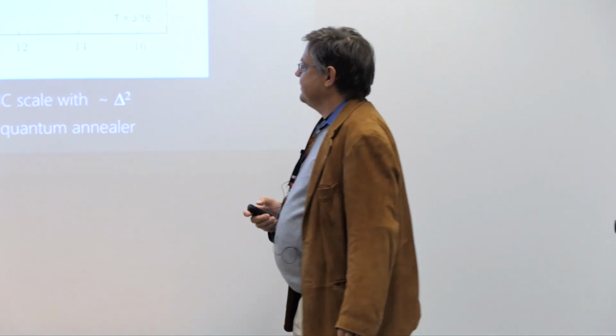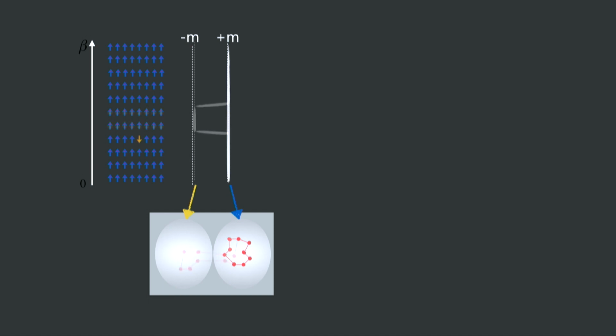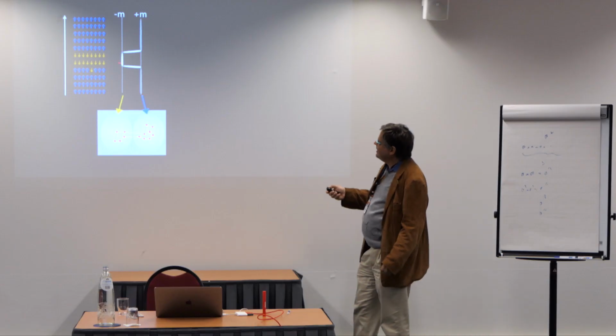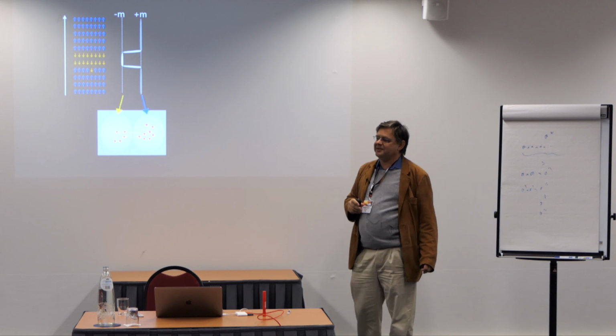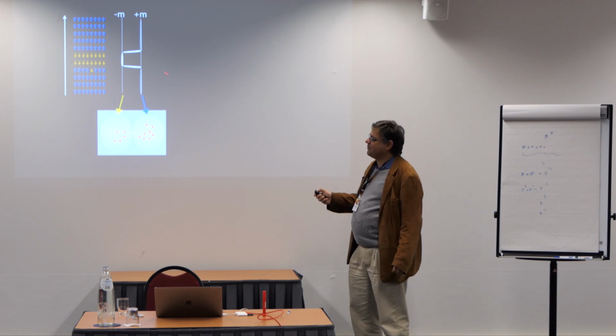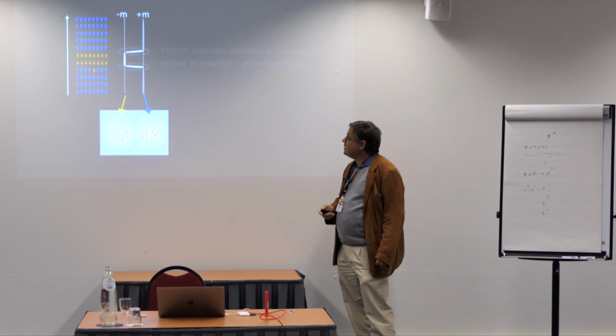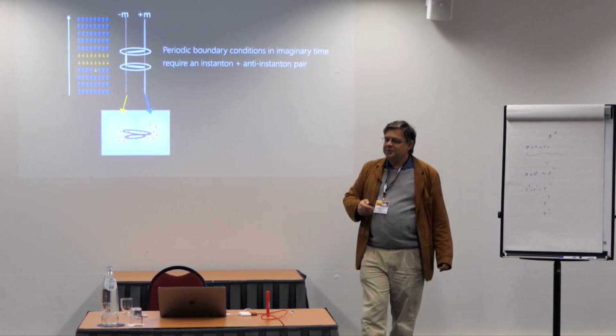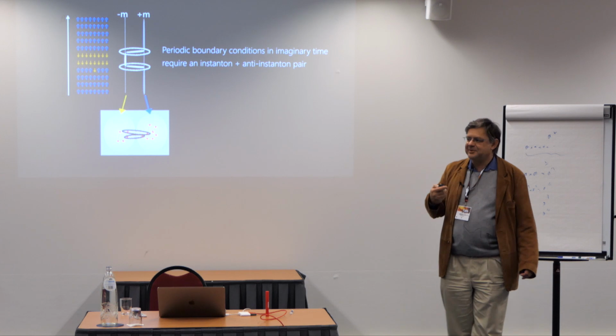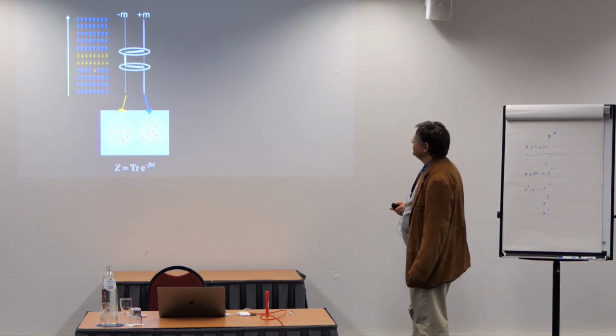But it gets nicer. Why is the scaling 1 over gap squared? Because when I do the path integral, that's the trace of exponential of minus beta H. So I have to go back to the original state. I start in a state, and after evolving to beta, I have to be back in the same state. So I have to tunnel through and I have to tunnel back. So I need to tunnel twice. And that gives me the 1 over gap squared scaling.